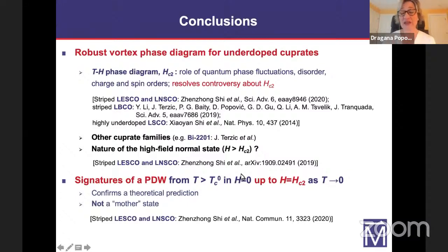One complication is that we have done those measurements, but in these materials, it is the rare earth ion that dominates the magnetization, in contrast to the copper spin moments. So yes, it has been studied, but it's very challenging to try to separate it. There have been some experiments in the past, primarily by Markus Hücker, who was able to determine and subtract the contributions of the rare earth. For example, one has paramagnetism, europium, and neodymium has ferromagnetic tendencies.